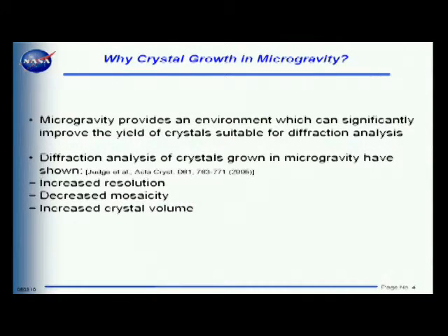Of course, increased volume means you have more of the protein molecule in the crystal structure. More protein molecule means more atoms, means more X-ray diffraction. But that's only half the story, because you can have a large crystal, it can be very low order, and you wind up with, let's go to the mosaicity, or the angle of difference between the individual molecules, which will